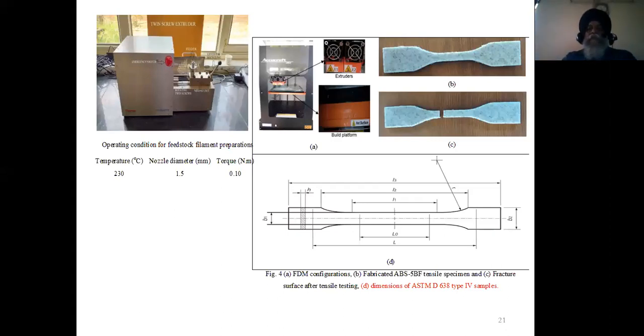So we printed the part for tensile, flexural, compressive as per the ASTM standard. Like you can see in this picture, the best wire we obtained at 230 degrees Celsius temperature of the extruder with nozzle diameter 1.5 and torque around 0.1 Newton meter. And this is as per the ASTM D638 Type 4 standard. And we prepared the tensile samples, and then we did some tests on UTM. We try to measure their tensile properties, right?